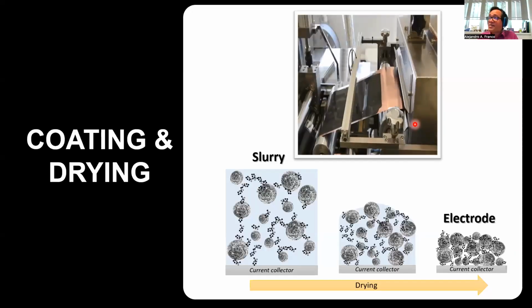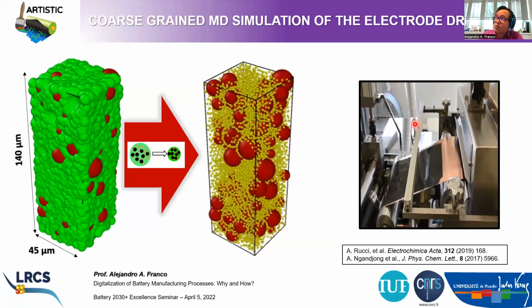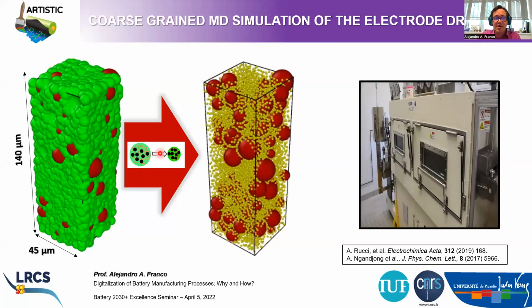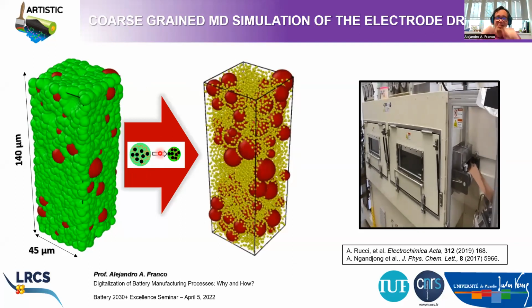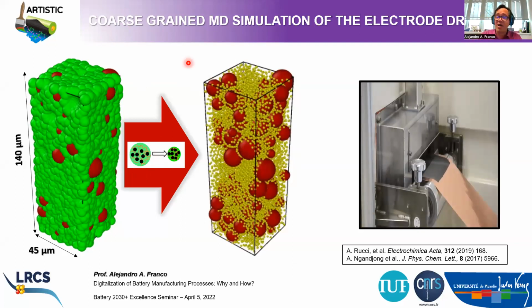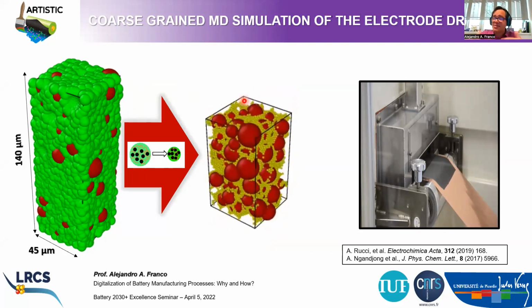The second step is the coating and the drying. And this is something that we also simulate using coarse grain molecular dynamics. And the way that we proceed is the following. We take this virtual slurry, we shrink the CBD particle size, okay, in order to mimic the solvent evaporation. Then all these green particles here representing the CBD, which initially contains carbon binder and solvent, become smaller. They are now represented here in yellow. Then the interaction forces between the particles change, and then we relax the system again.